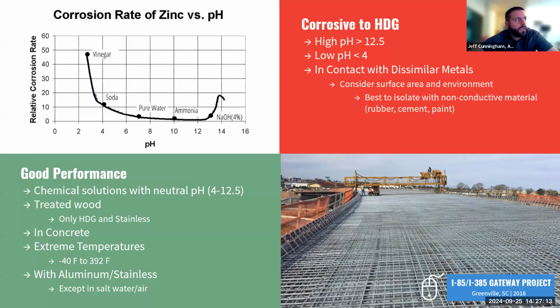I like to put up this slide, good performance versus corrosive. Good performance for hot dip galvanizing is anything with a neutral pH, 4 to 12.5. Treated wood can only be used with hot dip galvanizing and stainless. It does great in concrete. Hot dip galvanized rebar actually protects the concrete from outgassing and spalling. It's incredible. We actually offer a full hour on reinforced steel, and it lasts about 6 times as long as just black bar. It works really well with extreme temperatures, all the way from -40 degrees Fahrenheit to 392.